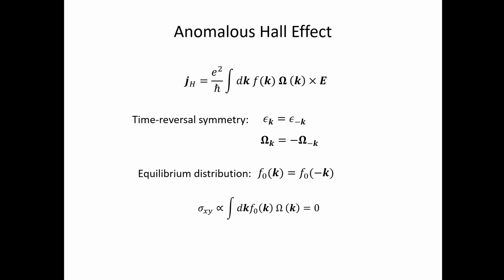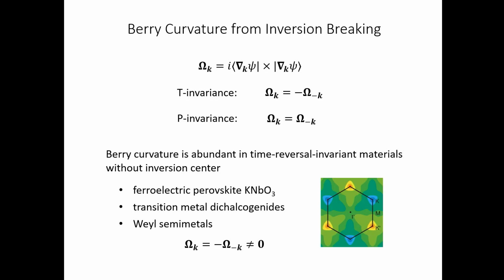Okay. On the other hand, I'm focusing on materials that are time-reversal symmetric. In this case, the Berry curvature can still be present, but there has to be equal and opposite Berry curvature at opposite momentum. At the same time, the electron's energy-momentum relation is symmetric. This means that if we look at the Hall current at the linear response level, we are integrating the Berry curvature over all occupied states, symmetric in k. So the distribution function is symmetric in k, and the Berry curvature is odd under k. Then this Hall conductivity vanishes. So for time-reversal symmetric materials, the Hall effect vanishes at linear order.